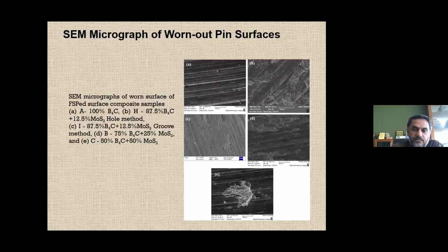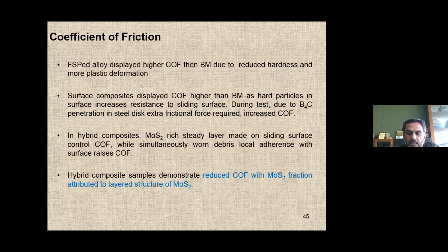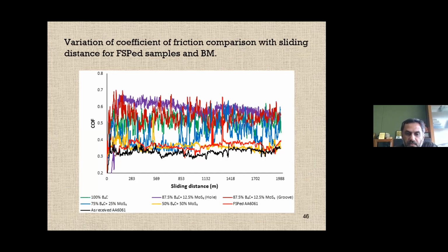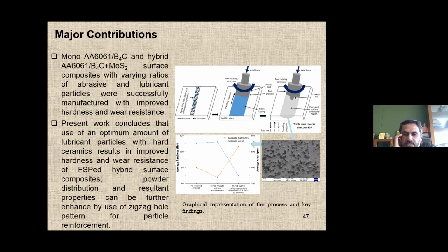And these are some of the SEM micrograph images of those surfaces, which indicate that you have both types of wear, adhesion and abrasion, which has been presented in those SEM micrographs. So this is another slide which gives you an idea about the coefficient of friction under the different compositions, starting from 100% B4C to the plain FSP also, and as-received 6061 also. So the major output of this study is that this B4C hybridization composition is the best, that too with the 12.5% MoS2, which is excellent.